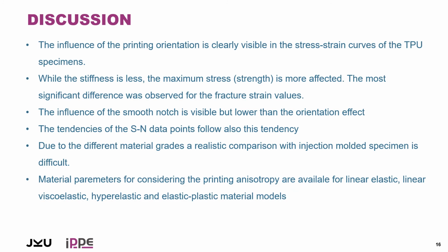Then, in a short discussion, we can clearly state that the printing orientation is clearly visible in the stress-strain curve. The stiffness and the strength are influenced, but the most important difference is observed in the fracture strain values. The influence of the smooth notch in the specimen geometry is visible, but it seems to be overshadowed by the printing orientation and the anisotropy effect. The monotonic and the cyclic tests revealed very similar tendencies.